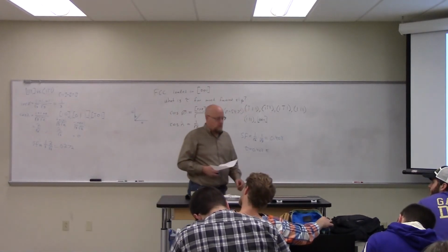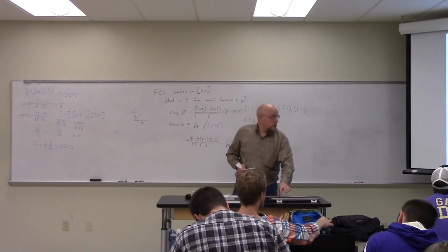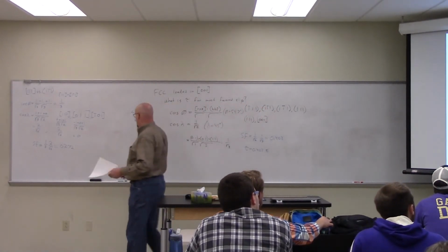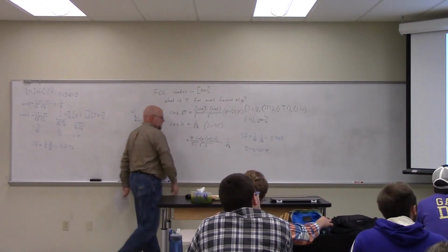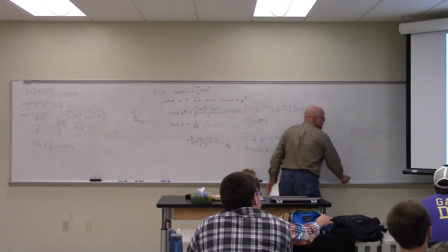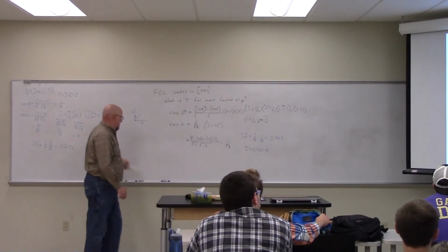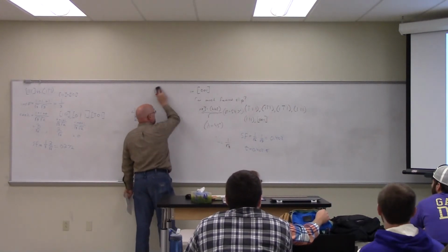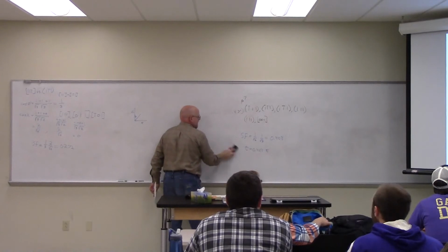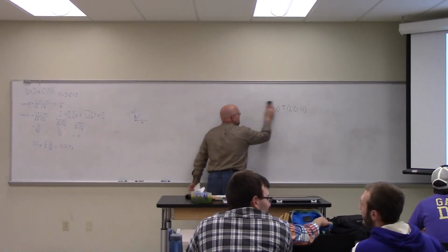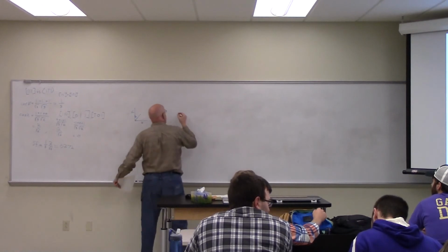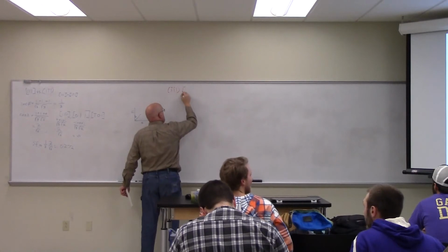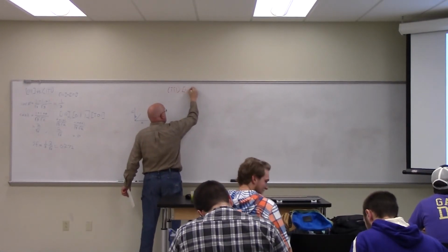What about that one? Which direction are we pulling? Oh, first off, we gotta identify the plane first. What's the plane? Using our ABC convention, 1 bar, 1 bar, 1. I'll buy that. So for the red one, we're talking the 1 bar, 1 bar, 1 plane, and we're pulling in the 111 direction.